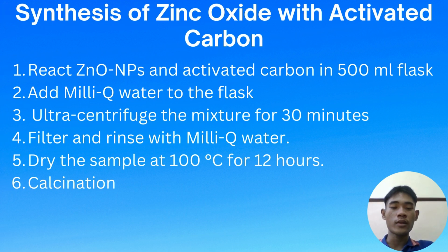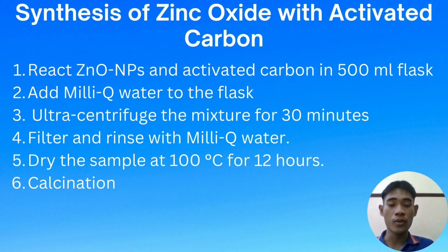Synthesis of zinc oxide with activated carbon. Step 1. React zinc oxide nanoparticles and activated carbon in a 500 ml flask. Step 2. Add Milli-Q water to the flask. Step 3. Ultracentrifuge the mixture for 30 minutes. Step 4. Filter and rinse with Milli-Q water. Step 5. Dry the sample at 100 degrees Celsius for 12 hours. And step 6.